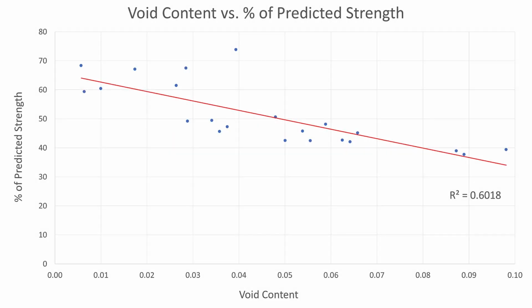There is a correlation between increased porosity and reduced strength relative to the expected strength based on fiber volume fraction, as seen in this graph. Porosity can reduce strength by reducing the effectiveness of the matrix at transferring load between fibers and between plies, which can reduce the strength of the laminate even if they have higher fiber volume fractions.